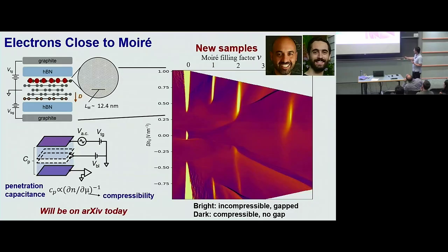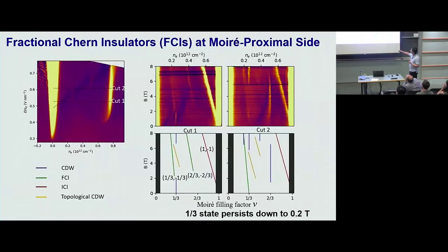Bright features here mean incompressible or gapped. And you find that this side here corresponds to when you polarize the electrons to the Moiré, and this side corresponds to when you push the electrons away from the Moiré. You can see there's a contact issue because there are a lot of random features here. And on the Moiré proximal side, what you can see is there are insulating states at filling factor 1, 2, and 3. And there's something here at 1/3 and 2/3. It turns out those 2 states are CDW states, or generalized Wigner crystals, when commensurate with the Moiré.